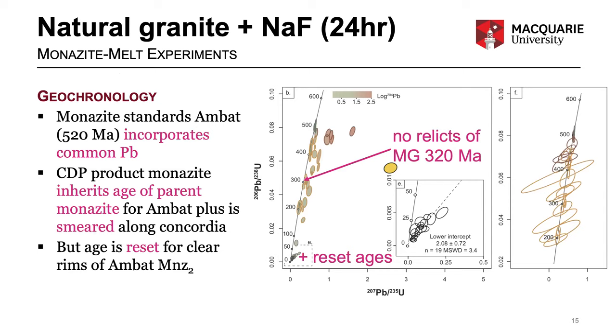After 24 hours, a significant proportion of those T4 rim domains have relatively reset ages. They're not perfectly reset to zero, but quite close to zero, and certainly on a trend that's heading towards zero with an intercept of 2 million years old. The problem with those grains is that they didn't reset neatly to zero.